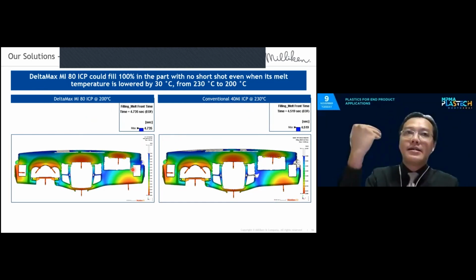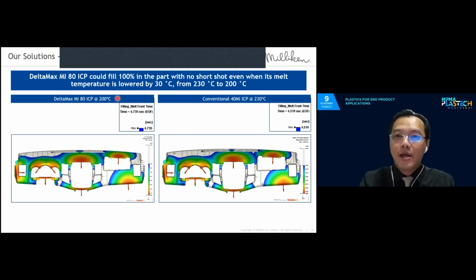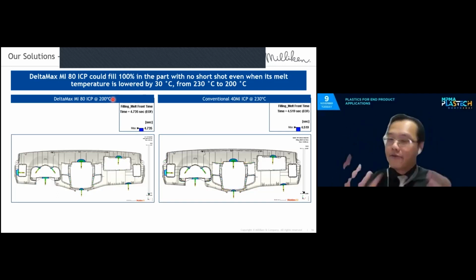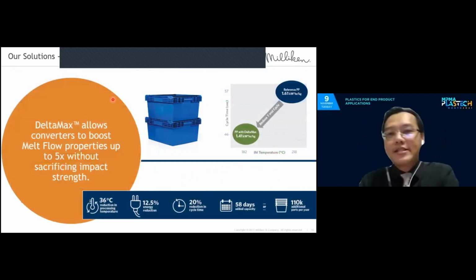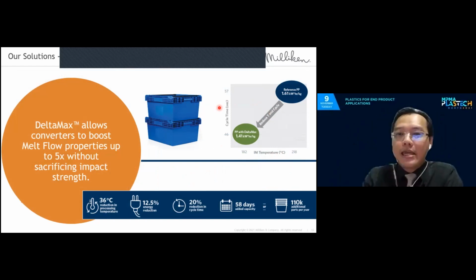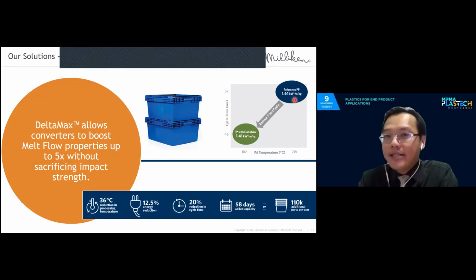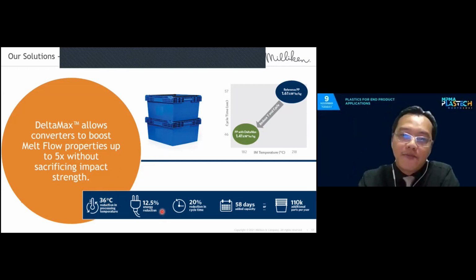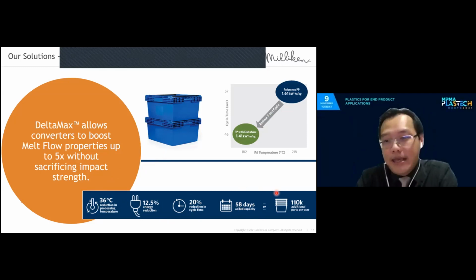So if you have higher MFR, you have the opportunity to reduce the injection temperature. And therefore, all that we have talked about in the last few minutes is also relevant, right? Reduce the cooling time and therefore increase productivity. This is a true example of crates. This particular example reduced the injection molding temperature from 218 to 182 degrees Celsius. And because of the cooler melt, you can reduce your cooling time and therefore your cycle time from 57 to 46 seconds. And you enjoy again the energy savings, the kilowatt hour. So 36 degrees temperature reduction, 12.5% energy reduction in cycle time. And for them, they had 58 days of added capacity, or 110,000 additional parts that they can produce, right? Because it increases